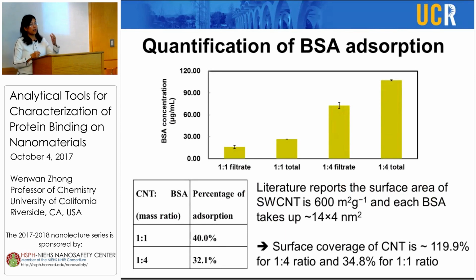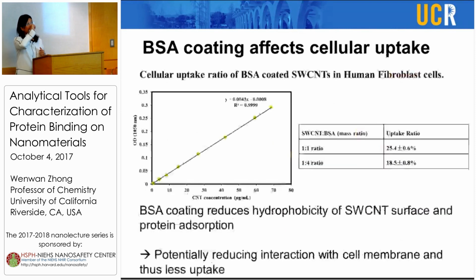But here we isolate the carbon nanotube and quantify the protein absorbed onto the particle, and also confirmed by measurement in the supernatant. So then we see that for coverage of the CNT surface, if we have a 1:4 ratio, then it's actually full coverage. But for the 1:1 ratio, there's still a lot of surface being exposed and not covered by BSA. And then we see how the uptake would be changed by the BSA coating. So when we have the 1:1 ratio of the labeling, we see the uptake ratio is higher than the one with more BSA coating. So we think it could be the thicker coating prevents certain interaction with the cell membrane, so then reduces the uptake.